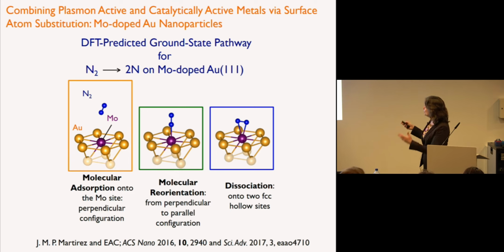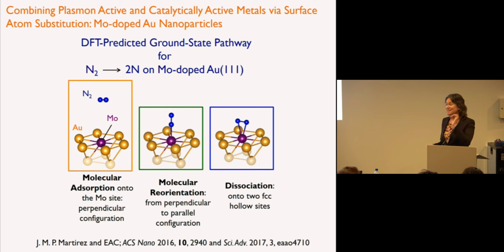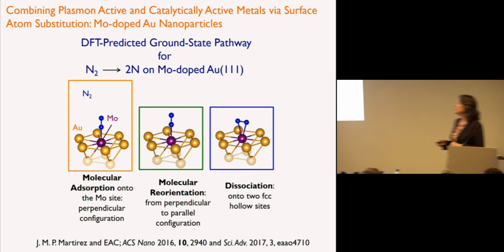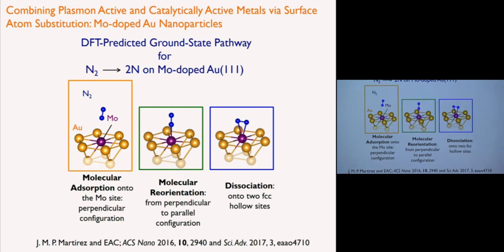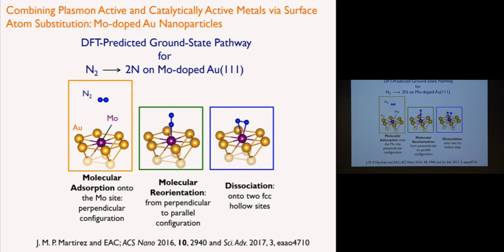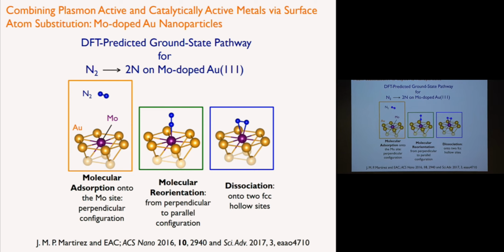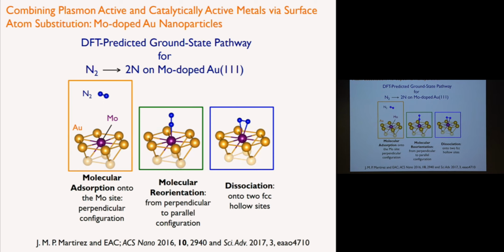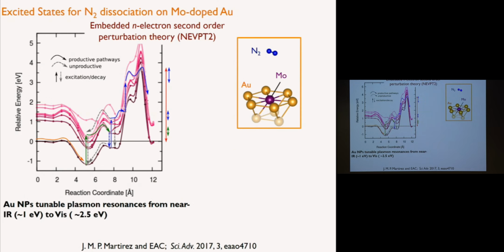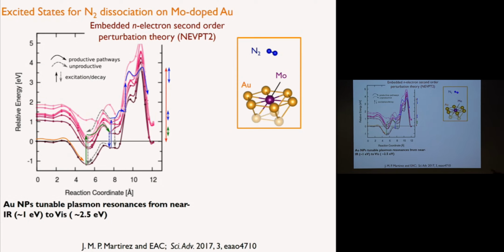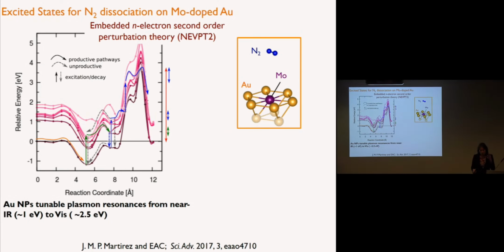So this is just a little cartoon showing you, from an actual calculation, the minimum energy path to form adsorbed nitrogen, and then the molecule reorients. These are the structures from the DFT calculations of the ground state, and then dissociation goes to two FCC hollow sites like that. So then what we do, as I said, is embedded correlated wave function theory. It's a multi-configurational theory that describes both static and dynamic electron correlation.